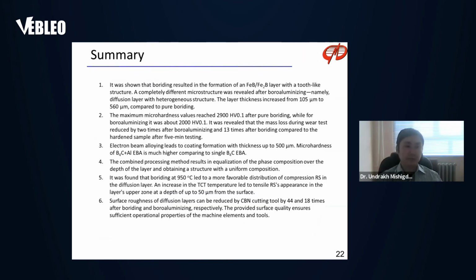So we came to the end of the report, and based on the conducted research there were several conclusions. Firstly, it was shown that boriding resulted in formation of an FeB and Fe2B layer with a tooth-like structure. A completely different microstructure was revealed after boron-aluminizing, namely a diffusion layer with heterogeneous structure. The layer thickness increased from 105 micrometers to 560 micrometers compared to pure boriding. The maximum micro-hardness values reached 2900 HV after pure boriding, while for boron-aluminizing it was around 2000 HV. It was revealed that the mass loss during wear test reduced by 2 times after boron-aluminizing and 13 times after boriding compared to the hardened sample